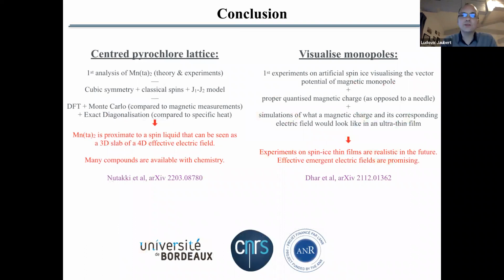And so this is my conclusion. On one side, in the first part, we showed how magnetic charges, magnetic monopoles, could be observed in electron holography. This was done in artificial spin ice, and we have shown how to do it in a thin film of a spin ice. And we have also shown you a new geometry, the centered pyrochlore lattice, which is the first really joint theory and experiment calculation and measurements on this material.